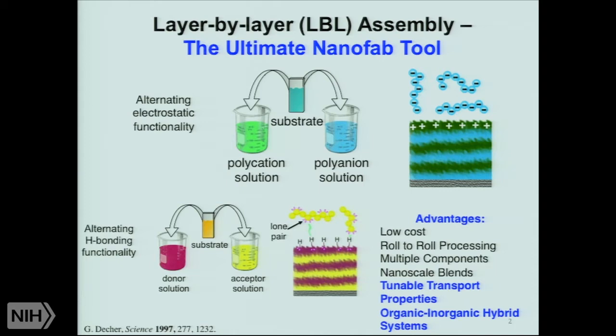Once you've adsorbed to the point of reversal, you can rinse off anything that's not truly adsorbed on the substrate and immerse it into another solution, again, oppositely charged, and that material system will adsorb.